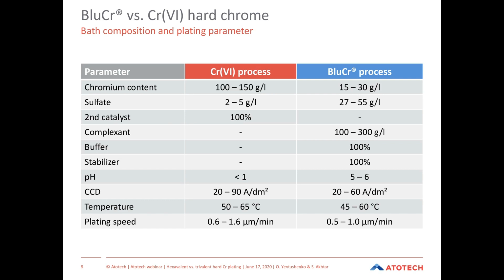There are no hazardous substances within the composition of the process. In this process, we have trivalent chromium ions, which are kept stable in solution using complexants, stabilizers, and buffering agents. The chromium content, of course, is much lower with a trivalent process compared to the Chrome 6 baths. So we're only operating between 15 to 30 grams per liter in BluCr versus 100 to 150 grams per liter as chromium content in the Chrome 6 baths. The operating parameters such as current density and temperature are very similar to Chrome 6 bath operation.